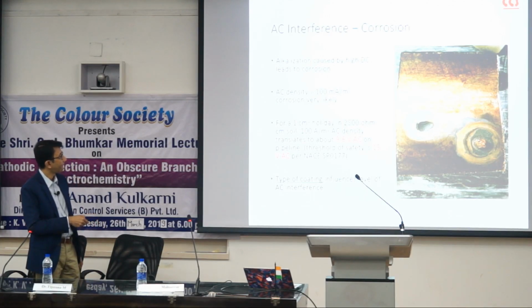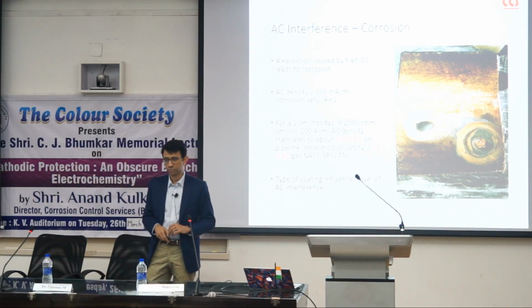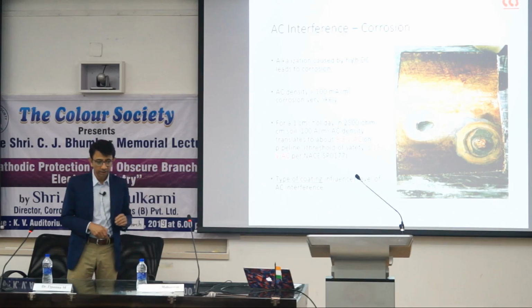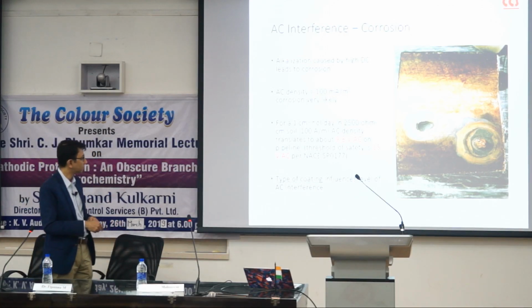But if you have high AC, the threshold for AC corrosion, this is the safety threshold. In case of a 1 centimeter square holiday in a 2500 ohm centimeter soil, it is just 9.8 volt AC. So today we have the specter of AC corrosion, which has created a serious problem in pipelines all over the world, because we find pipelines not only have high quality coatings, but they also run parallel to high voltage AC overhead lines, and that causes a lot of AC interference. So the type of coating influences the level of AC interference in a very significant way.